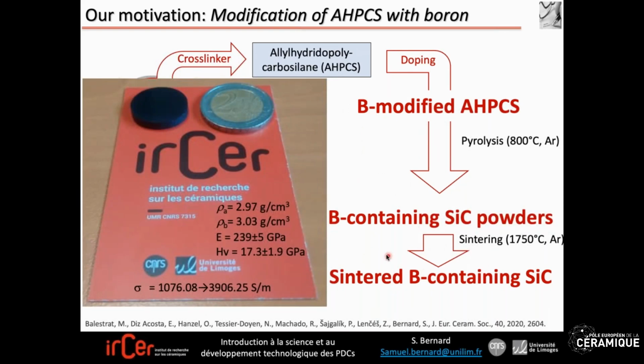And because of the addition of boron at molecular scale, we can sinter these powders at a temperature as low as 1750 degrees C to form a nearly dense silicon carbide object with a relatively high hardness, as you can see here, and an electrical conductivity which can be controlled through the amount of boron you use at molecular scale and the temperature of sintering. But just by adding boron in your polymer, you can significantly reduce the temperature of sintering of silicon carbide by 400 degrees C, which is not so bad.